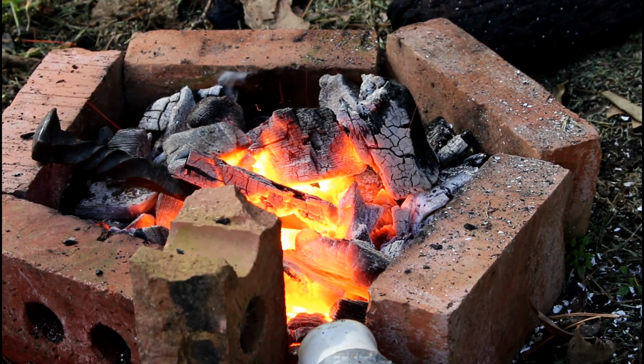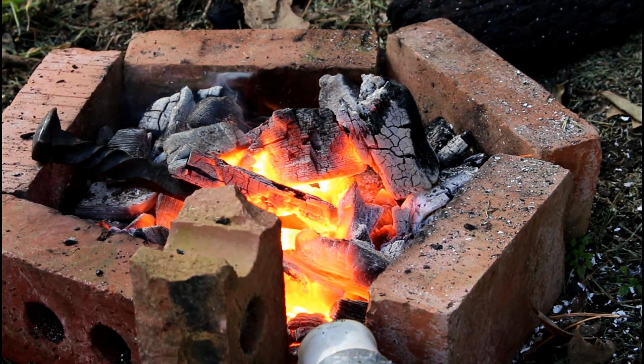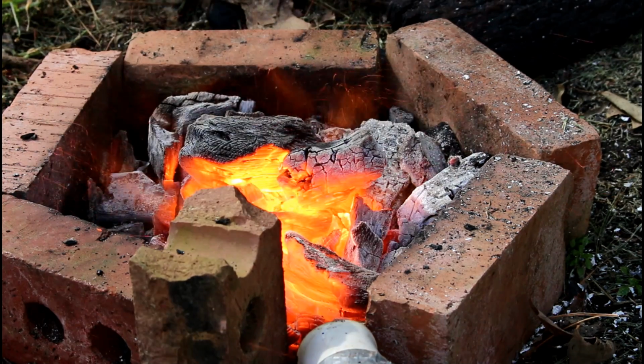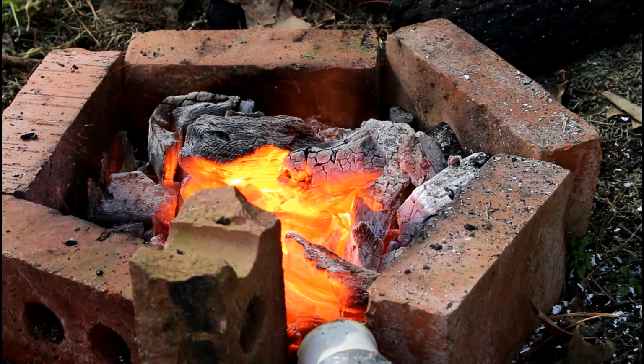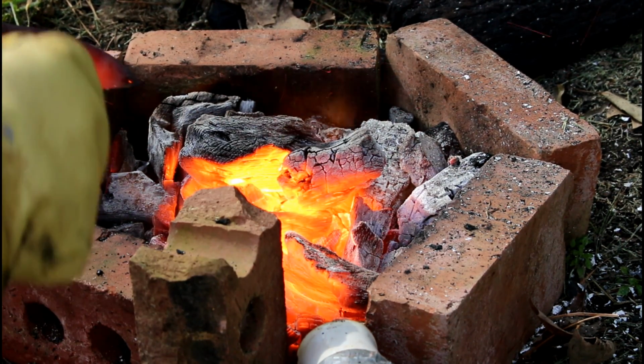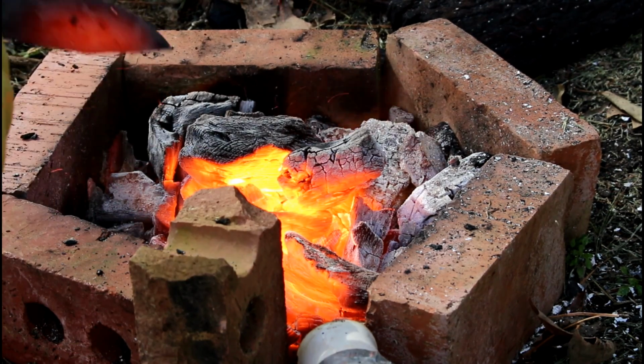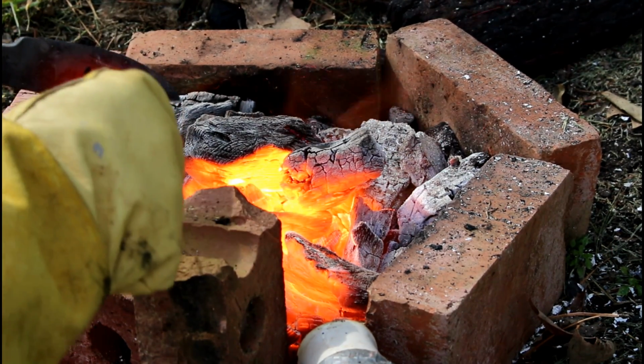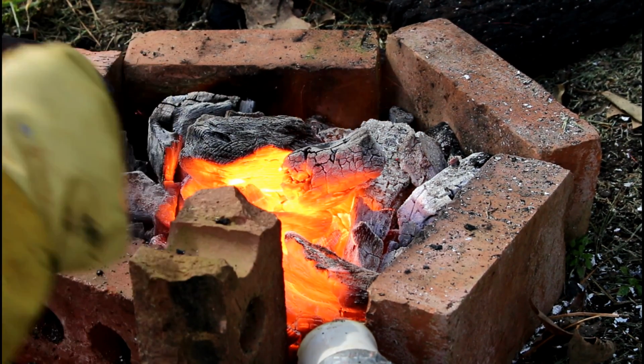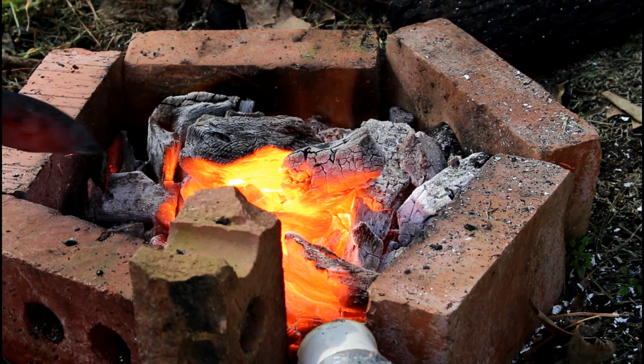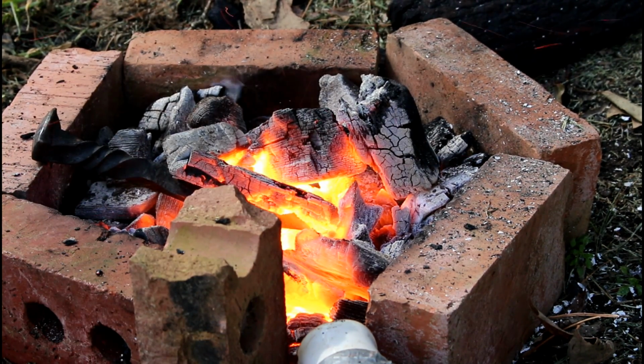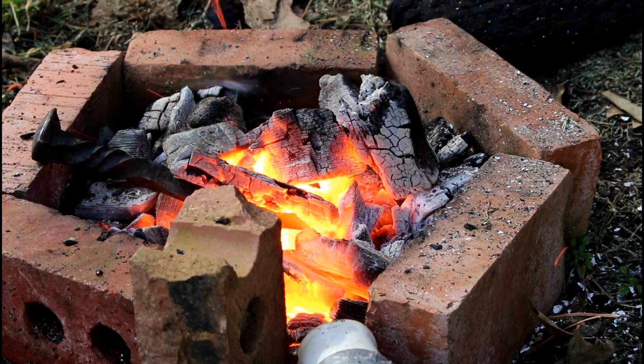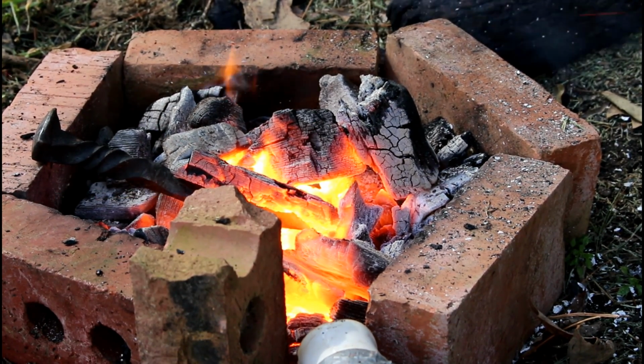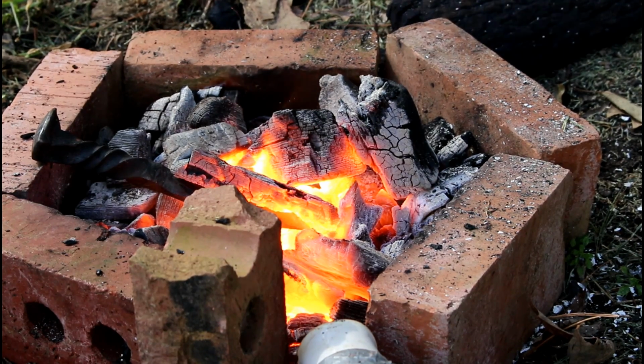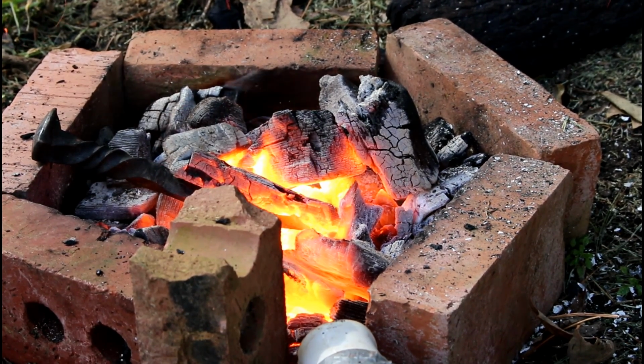It is an interesting property of steel that it ceases to draw a magnet when it hits 1345 degrees Fahrenheit. The critical temperature of high carbon steel is around 1475 degrees. As the steel heats up, touch it to the magnet every few seconds. When it stops sticking to the magnet, you know you are close. A few seconds longer, or until the steel has shifted color a notch brighter, and you know you have hit critical temperature, approximately 1475 degrees Fahrenheit.